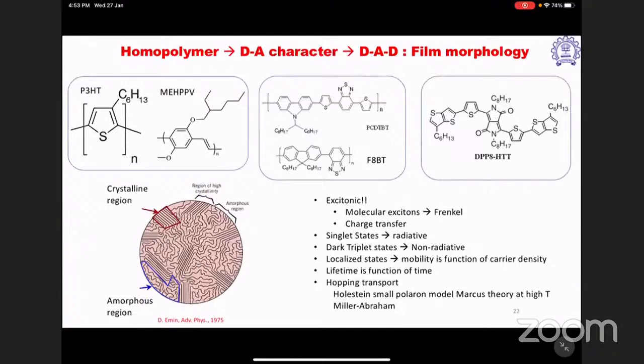Those are Wannier excitons. If you cool down those materials, you can see the excitonic peaks in even those semiconductors. But at room temperature, the excitonic binding energy being less than 10 meV in those systems, we generate free charge carriers. Whereas the excitonic binding energy in excitonic, molecular, or organic semiconductors is in the range of a few hundreds of meV. So a single organic semiconductor cannot generate photocurrent. You need to dissociate that exciton, and for that we have to do something additional to what we do in the case of silicon and gallium arsenide.